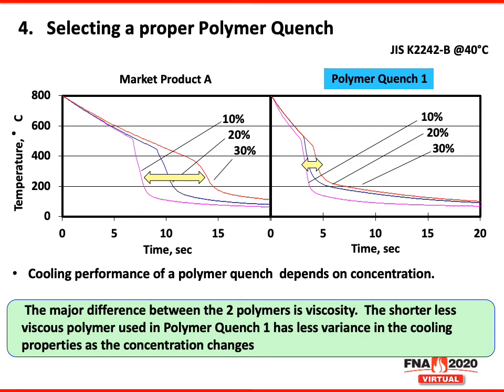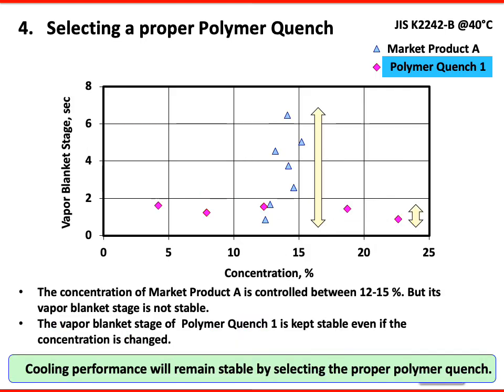The shorter, less viscous polymer used in Polymer Quench 1 here provides more uniform cooling and more uniform vapor blanket lengths, which is shown here. So by controlling it between 12 to 15%, which is a very common concentration, market product A has a vapor stage all over the place. Whereas you can see the vapor blanket phase for Polymer Quench 1 is more tightly controlled. And the cooling performance will remain stable if you select the proper polymer.